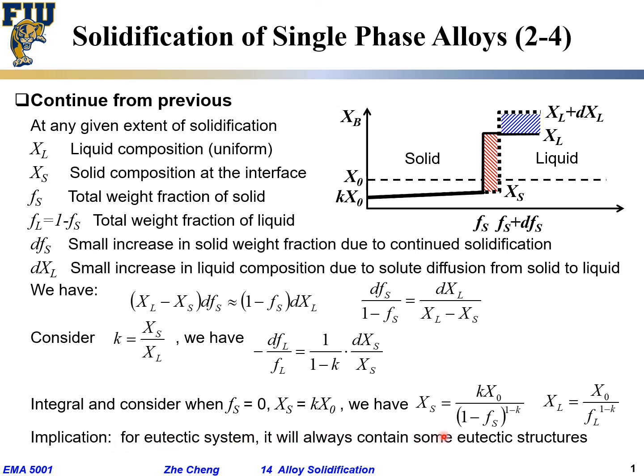And the implication would be the system would always contain some so-called eutectic structure. The system would always contain some eutectic structure. As FL goes smaller, this term would go typically as FL, less and less liquid. K, as we mentioned, is greater than 1 or smaller than 1. Remember the phase diagram, K is smaller than 1, which means 1 minus K is positive, right? So I have FL going towards 0, which means I have less and less liquid.